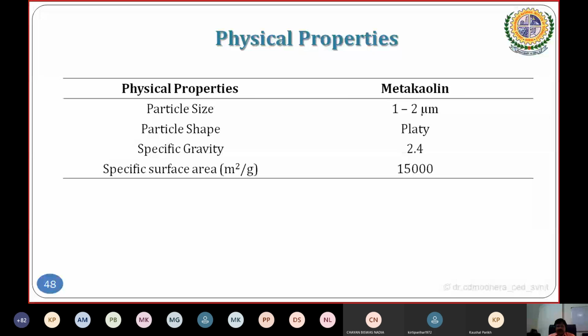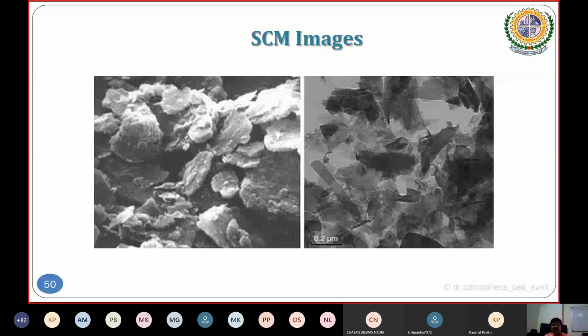And you can see its SEM images. You can see directly that they are not circular but plate kind of images, which directly indicate its shape as plates, magnified by 1000 times and 0.2 micrometer, I think it is written. This is just to visualize the micro level shape. Here with metakaolin, we can see 10% metakaolin as a replacement of cement is beneficial over higher dosage.